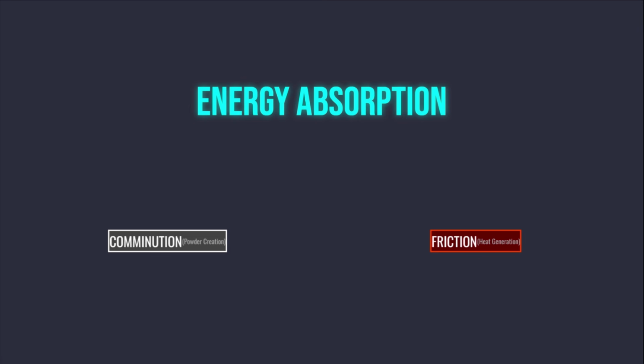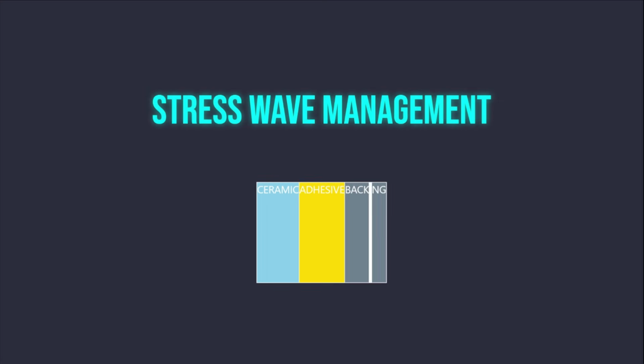Beyond fracturing the projectile, the ceramic layer absorbs energy through two primary mechanisms: comminution and friction. Comminution is the process of the ceramic tile breaking down into fine powder, consuming energy through the creation of new surface area. This process is highly efficient in dissipating the kinetic energy of the impact. Simultaneously, the interaction between the fractured ceramic fragments and the eroding penetrator generates significant frictional heat, further slowing the projectile.